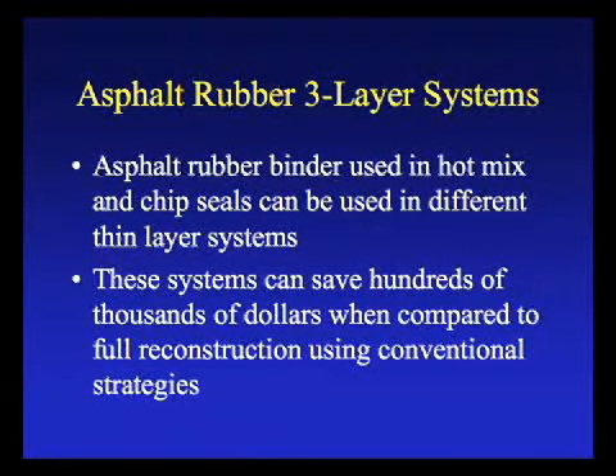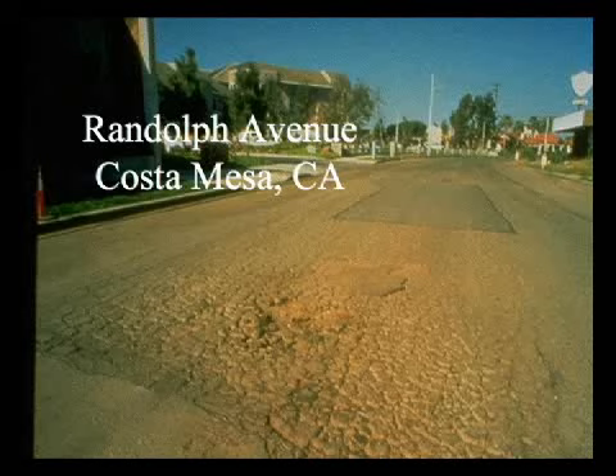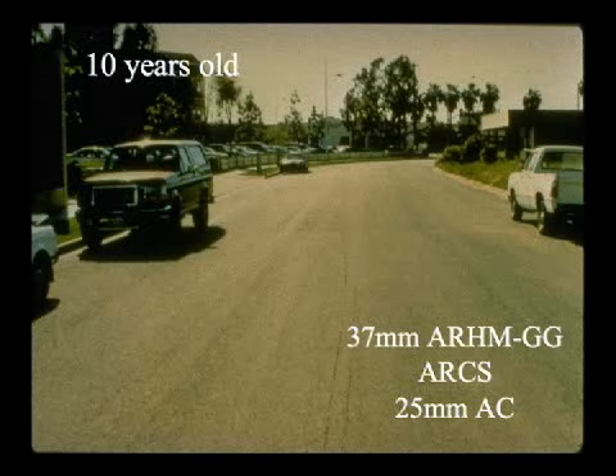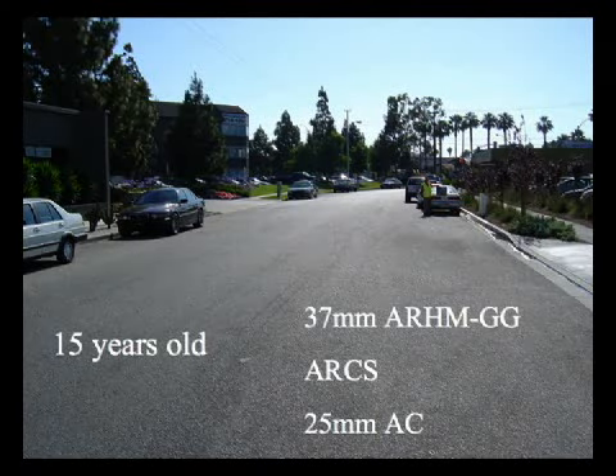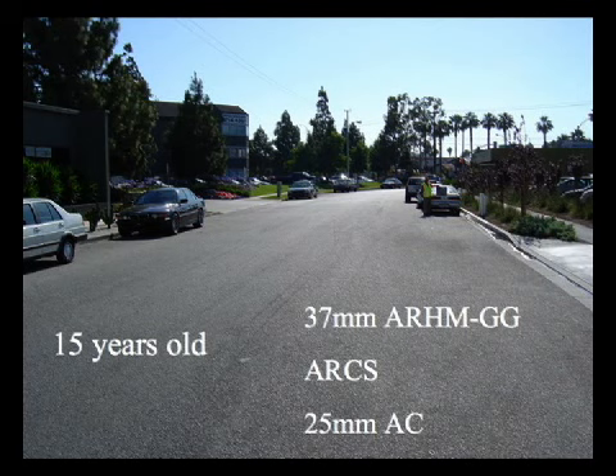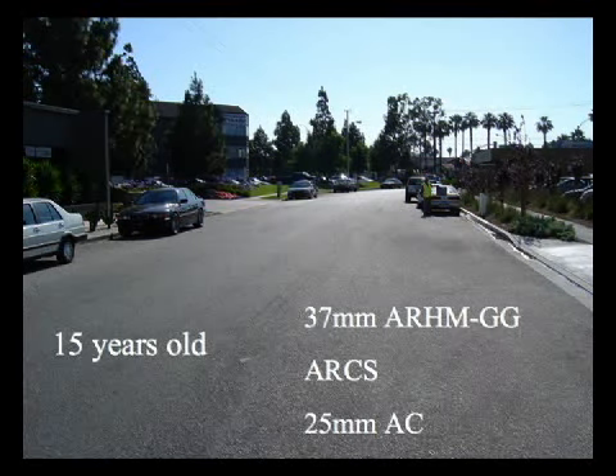I'm going to tell you now about the three-layer systems and how well they can perform. Here's a project that I followed from the very beginning, and what you do is you talk about, well, this rubber looks pretty good, but it's kind of hard to believe that you're going to get any kind of life out of this. This is what it looked like. They came in and put a 25 millimeter nominal overlay leveling course on it just to level it up, put a chip seal as a SAMI, and 37 millimeters of gap-graded mix. This picture was taken at 10 years. Well, this year was the 15th year of this project, and here's a picture that was taken at the same location. There's no cracks in the entire pavement. There's a cost analysis in my paper on this project. I think it saved $52,000.